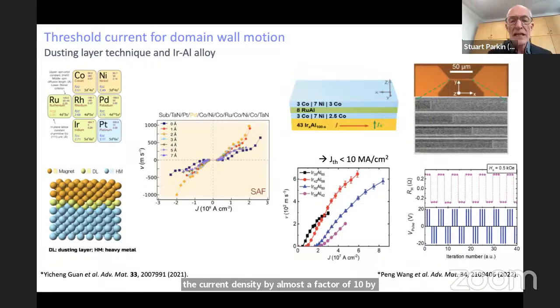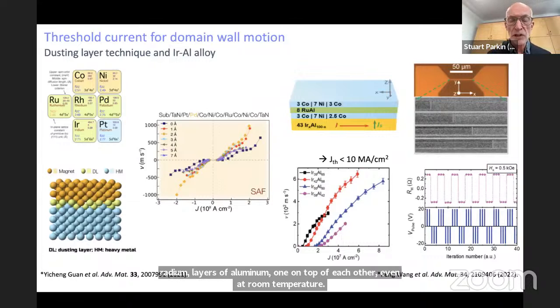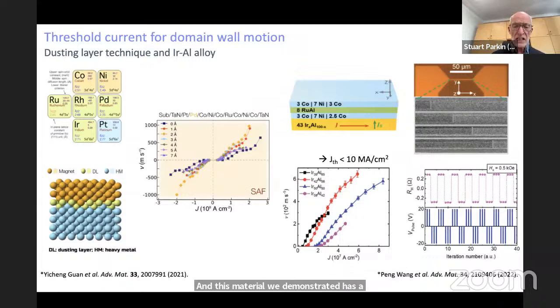These are formed from an iridium aluminum, roughly 50-50 alloy, which forms an atomic arrangement of layers of iridium and layers of aluminum, one on top of each other, even at room temperature. And this material we demonstrated has a huge spin Hall effect, the conversion of current to spin, which is many, many times higher than in platinum, the typical material. This leads to the significant reduction in the strength of the threshold current to move the domain walls, as shown in this image in the bottom, in the middle.